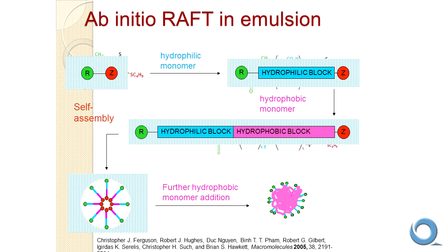Once the polymer forms, we have a hydrophilic end with ionic groups at one end. We're using, in this case, as an example, acrylic acid as our hydrophilic monomer. And then we have it capped on the end by this chain transfer group. So this is a macro chain transfer agent.